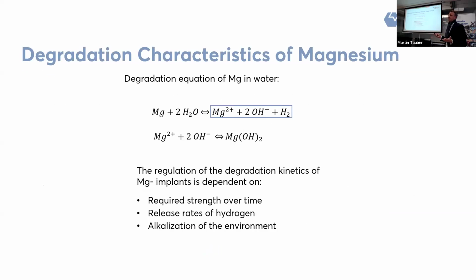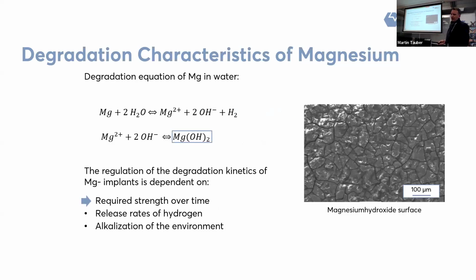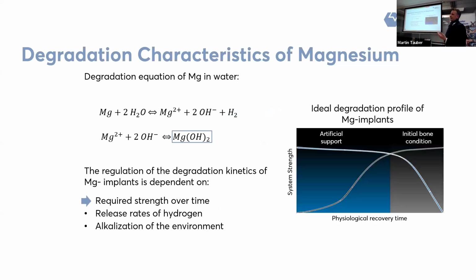All right, we see there's a lot happening in just this equation, and we have to go a few more steps from here, because the magnesium ions and the hydroxide ions that are released usually form a magnesium hydroxide layer. That's what is shown in the second equation here. And this layer looks, as shown in the picture, cracky, it's not dense, and everyone here and also online can imagine that this layer is not contributing to any load-taking capacity of the base material. So as this layer arises, the implant already suffers a loss in strength. And this is exactly what is expected and what is wanted. But we have to make sure that this loss in strength does not occur too early.